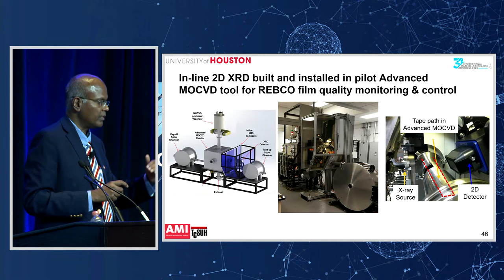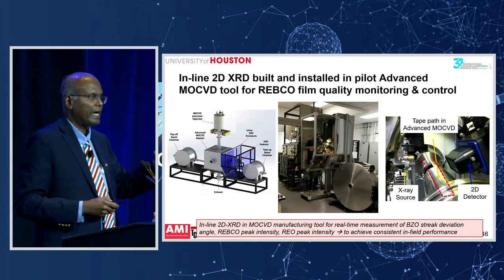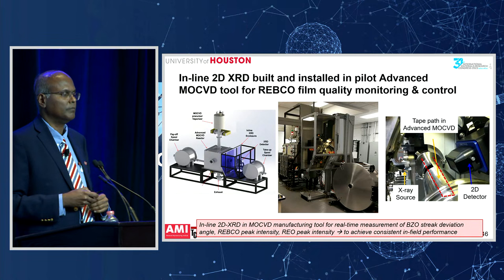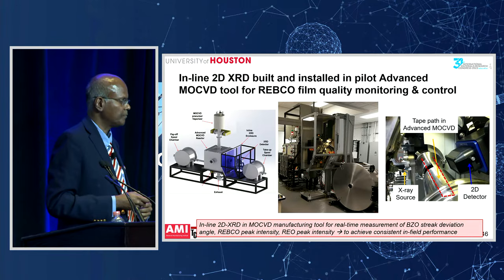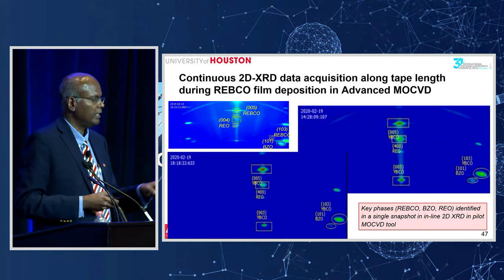And so while you're making the tape, you can actually monitor the various peaks in real time, get an idea of the composition of the film, in addition to the texture and the orientation and other phases. So here I'm showing actual data obtained from a 10 meter tape and a 5 meter tape. You can see the diffraction peaks obtained in real time as we're making the tape. The tape is moving while you're getting the data.